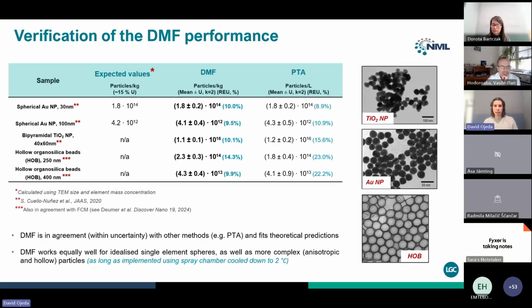As we can see in this slide, the performance of the DMF has been checked against different types of nanomaterials, from the simplest case, spherical gold nanoparticles of two different sizes, 30 and 100, to far more complicated scenarios, such as titanium dioxide nanoparticles, which were no longer spherical but bipyramidal, and also organosilica beads of different sizes.